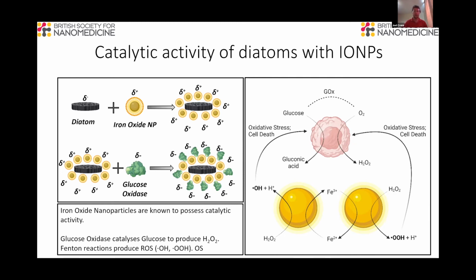This has a dual approach in the sense that, going back from there, under this concept, we then attached iron oxide nanoparticles to the diatoms using electrostatic interactions again. We then also attempted to attach glucose oxidase to the iron oxide nanoparticle-coated diatoms with the intention of further promoting the biochemical reactions in the cells.